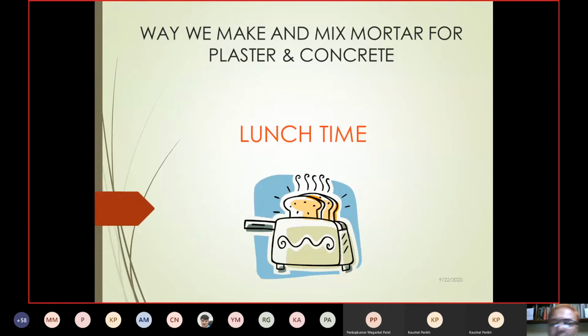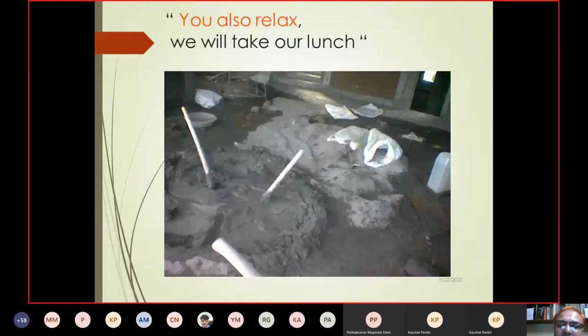Then during lunch, what do they do? Scenario: at 1 p.m., whether it is plaster mortar or concrete mortar, they stop the work. The initial setting time of cement is 30 minutes. They pour the water at 12:30 or 12:45 and start working at 2, after more than 1.5 hours or 90 to 100 minutes, and this mortar is idle. We are not getting the achieved strength. If it is plaster, there will be a crack and it will fail. If it is concrete, we are not getting the strength.